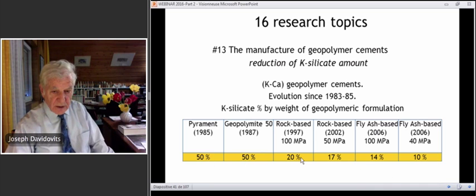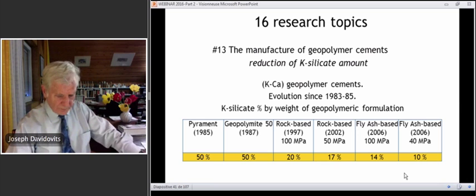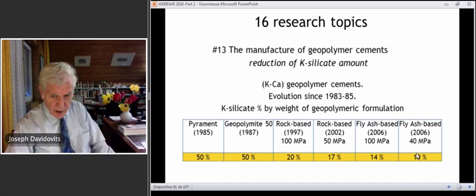So we started from 50 to 20 for 100 MPa, to 17 for 50 MPa, then for fly ash based 14%, and from fly ash based 40 only 10%. So if you remember my answer to the question, is the liquid more expensive than Portland? You see, when you only have 10%, then it doesn't matter. If it is 5 times more expensive than Portland, then it is still 2 times cheaper than Portland. The target is to reduce to minimum the quantity of the silicate, because this is the one that is the most expensive and the most difficult to manufacture.